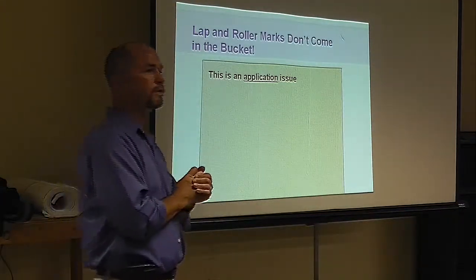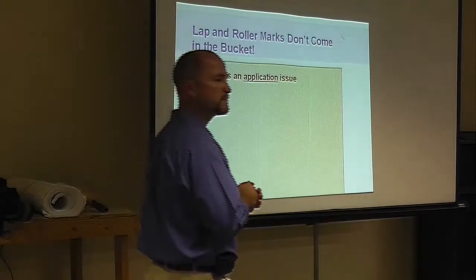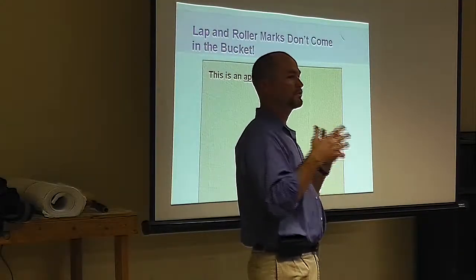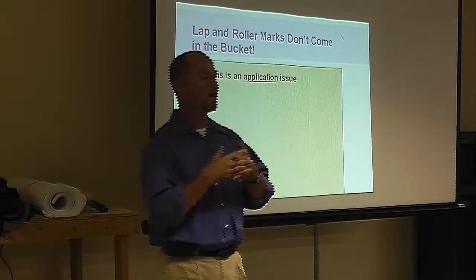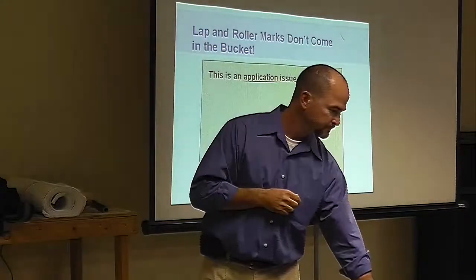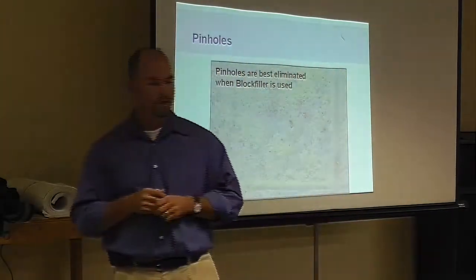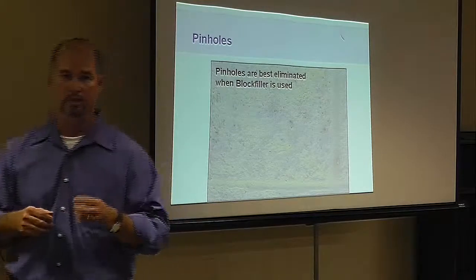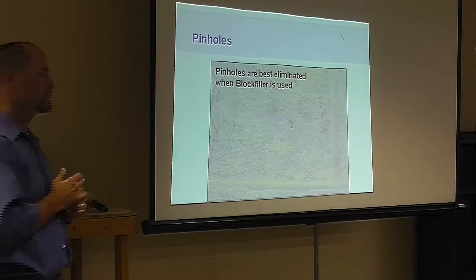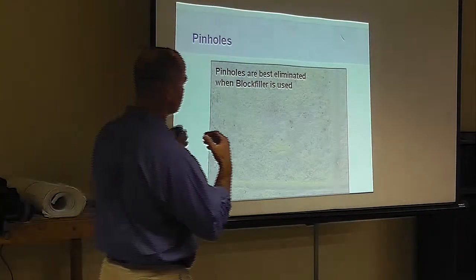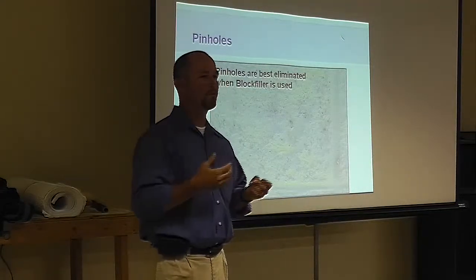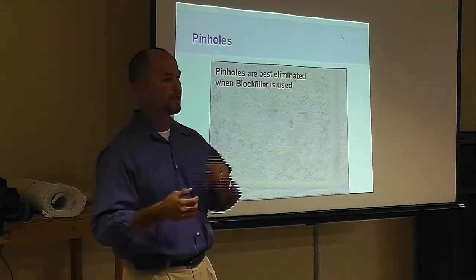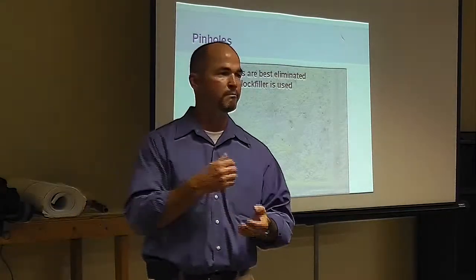Same thing when it's really cold. Sometimes you have to go to a solvent-based material, but it's so cold, the coating won't coalesce and it won't bond as well. Pinholes. When we're doing CMU block walls, we like to see a block filler go on there first. Because, like I said, if it's got pinholes in there, it's going to allow moisture to get in and get behind the building. A lot of times when you get moisture inside a building, that's when you have mold and mildew start happening.